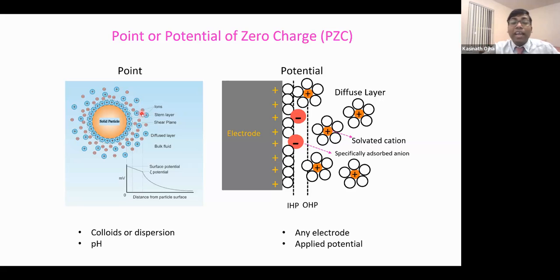In that case, the ions also have a distribution at the interface, and that can be monitored basically via pH. At a particular pH, the net charge on those particles will be zero. So at that pH, we call it the point of zero charge. But for electrodes, if you put them in electrolyte and apply a certain potential, and at that potential the net charge on the surface is zero, that potential is called the potential of zero charge. I think it's clear to understand. If you don't understand, let me know.